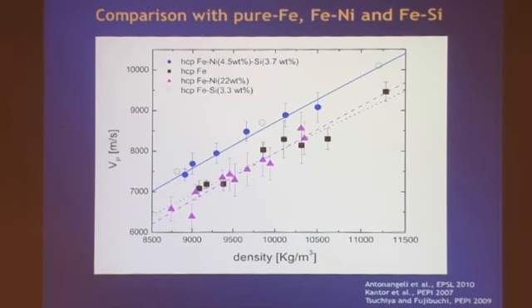overlap, at least they're within the experimental scattering, while adding 3.7 weight% of silicon makes the sound velocity systematically faster, as better highlighted by the linear fit to data. This difference is about 9%. The notion that the sound velocity increase is solely due to the presence of silicon is further supported by a good agreement between our result and ab initio calculation on a FeSi sample of about the same silicon content, this open symbol, that are in quite good agreement with other result.